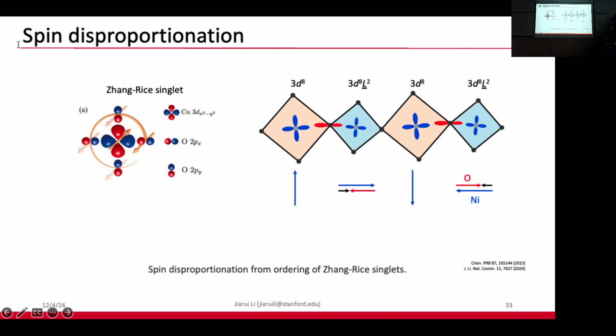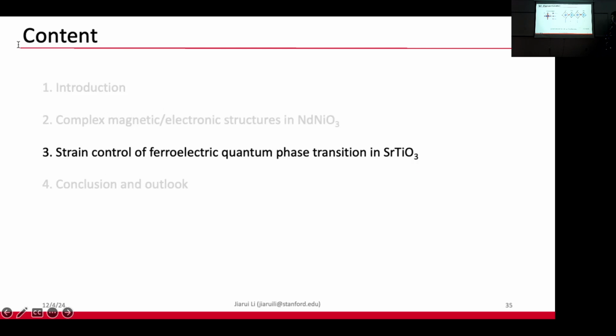So we're thinking here, like in our picture, we have 3d8 clusters on one side and 3d8 with 2 ligand holes on the other side. And what we believe is that we have nickel spins that are the same on each side, but then the oxygen ligand holes form this Zhang-Rice singlet-like structure to reduce the spin size on the compressive nickel-oxygen clusters. So in the end, we ended up with this period-4 magnetic structure with a large spin, small spin. So we call it this spin disproportionation phase.